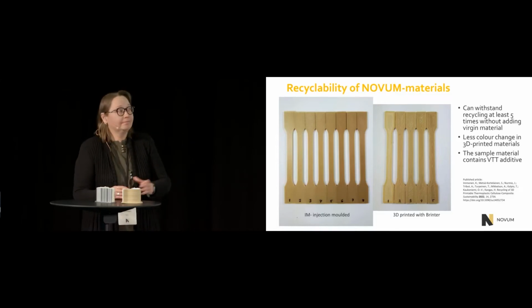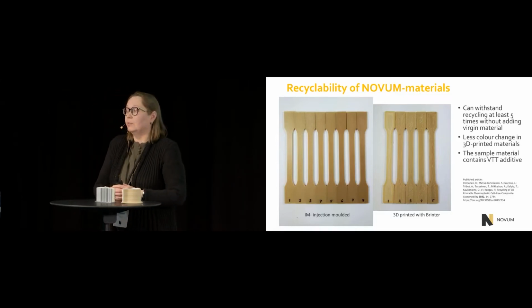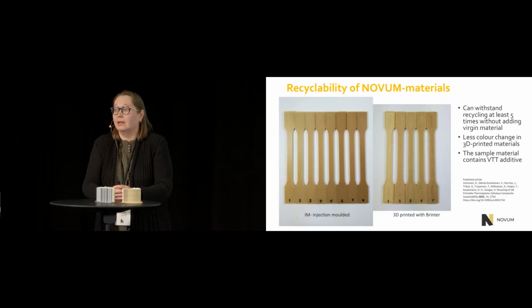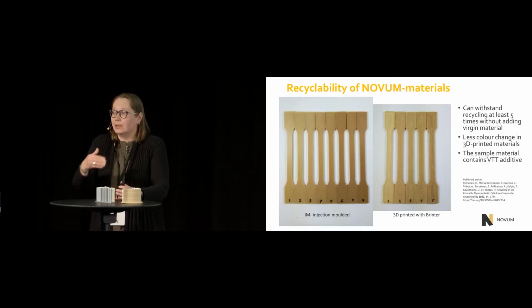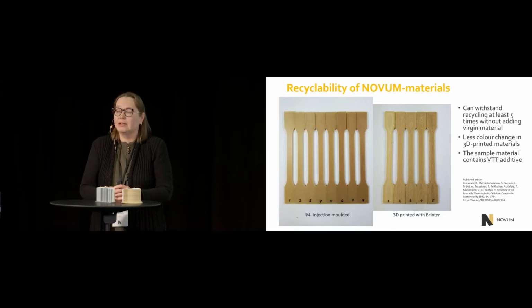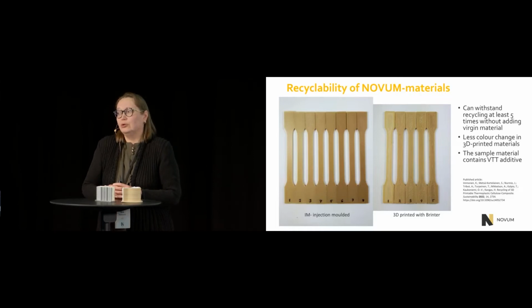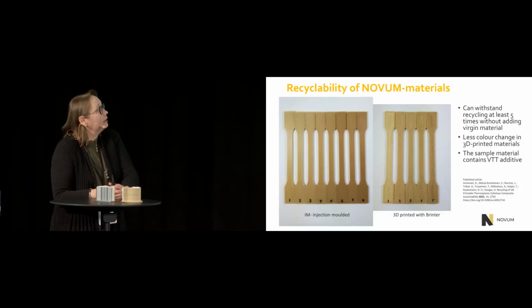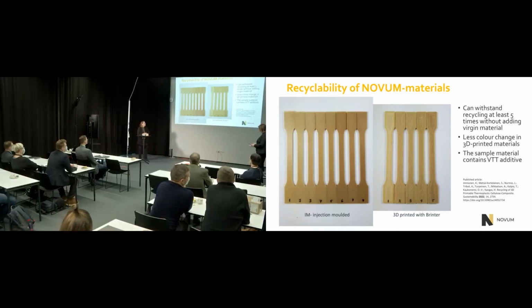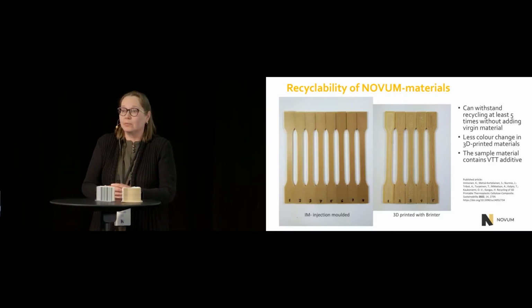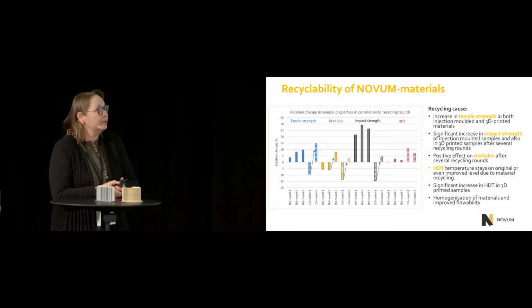You can see some injection molded samples and 3D printed samples here within the different recycling rounds, that there is a little bit of color change, mainly coming from the microcellulose, but not too much perhaps. And even though the color is anyway quite light beige, it is still usable after 5 recycling rounds. More you can read from our recently published article.